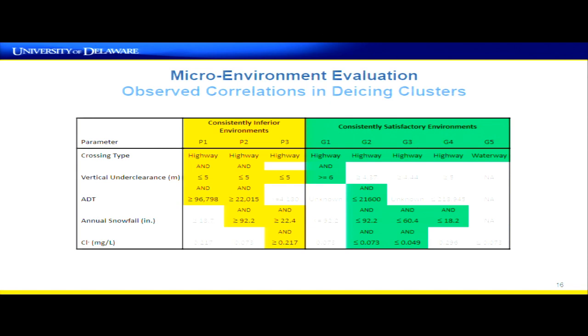We also made similar conclusions based on what we call the de-icing clusters in Maryland and New York, where again, the consistently inferior environments were highway crossings with a vertical underclearance of 5 meters or less. And then also having certain combinations of a really high ADT or a more modest ADT but a lot of snow, or a smaller level of snow but a lot of atmospheric chloride concentration. So those were things that emerged as observations based on, here I need to qualify, this is 40 out of about 4,000 bridges that could be in this category. So this is a more limited analysis. But what is ADT?